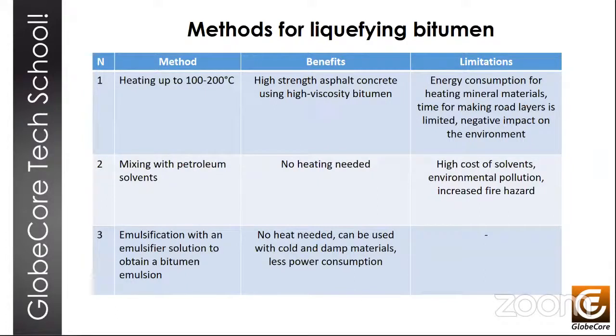The third way to have our bitumen in liquid form is to emulsify it with water, adding an emulsifier, a surfactant. When we emulsify bitumen, we get the emulsion, which remains liquid even under normal ordinary temperatures of about 20 to 30 degrees Celsius.